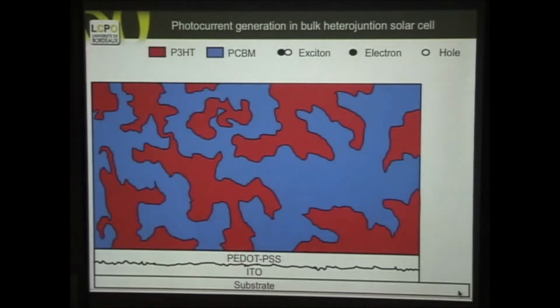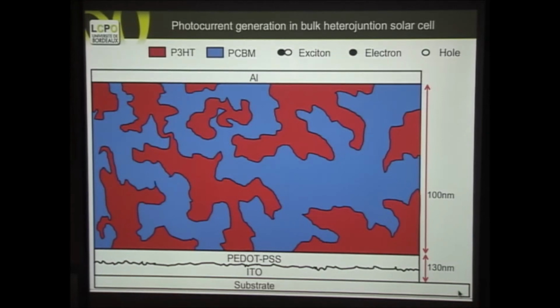Here you have a substrate, which can be PET, we call it, and the indium tin oxide, the transparent electrode. We put a conjugated polymer, a polythiophene complexed with a polysulfonated styrene. Essentially, we put it to remove the roughness and also to protect the indium tin oxide, so that the indium doesn't move and go up into the device. And we use a blend of materials. And then on top of it we put, well, these are the thicknesses just to compare things. It's 100 nanometers, sufficient for this kind of device to absorb enough light, since I told you that the strength of absorption is much larger than in inorganic crystals, and you have also an aluminum electrode. So the ingredients are a polythiophene and C60, the carbon, the blue material.